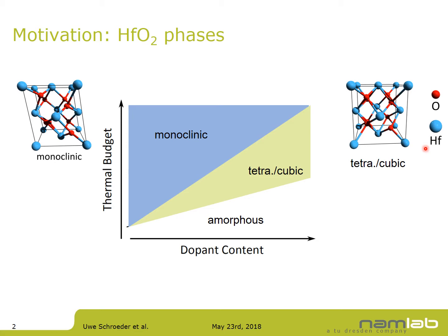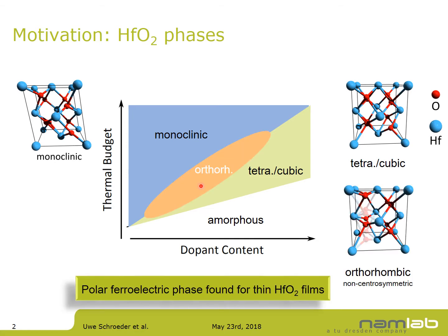But then when we were looking at hafnium oxide for DRAM applications, we found at the phase boundary between the monoclinic and the tetragonal cubic phase of hafnium oxide — for thin layers, typically in the order of 10 to 15 nanometers — the ferroelectric properties of the material, which was later confirmed as the orthorhombic Pca2₁ phase of hafnium oxide.